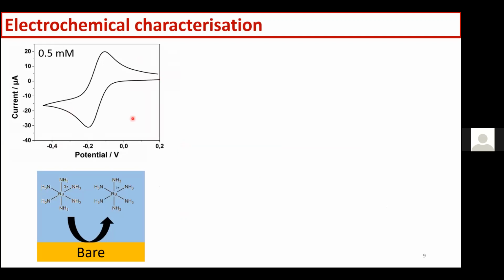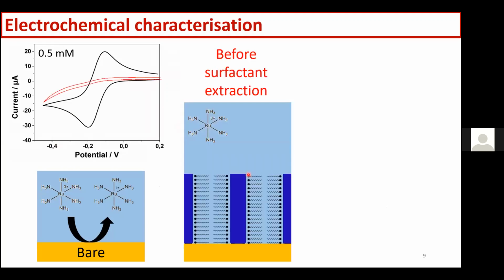electrode. And so when we deposit the film, before we extract the surfactant, this is a schematic of how the surface looks. So we have the surfactant still present inside the pores, and the electrochemical response for the probe is almost completely suppressed by the presence of the silica and the surfactant inside the pores. Then if we do the extraction of the surfactant, which can be either by